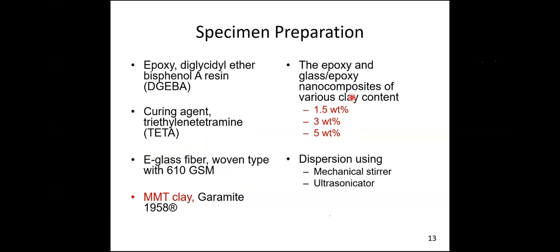You may ask a question: why have I chosen 1.5, 3 and 5? Why have I not gone beyond 5? The reason is, as I mentioned earlier, it is nano fillers. So if I increase the clay content, then we may not mix the clay well with the epoxy. That is why we stopped at 5 percentage. We have chosen 3 different weight percentages in order to understand which content would be the optimal content for getting better mechanical properties.